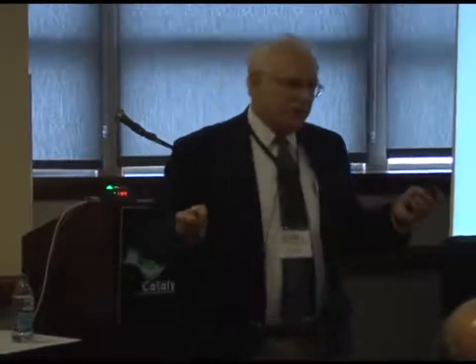But when we have iridium nearby, it activates hydrogen much more facilely than rhodium does. It spills over. We see that in the IR. OH goes to OD with D2. And what happens is that somehow the spilled over hydrogen is interfering with the bonding of the ethylene to the hydroxyl group. And so it's mostly shutting down the dimerization route, and by default the hydrogenation route takes over.